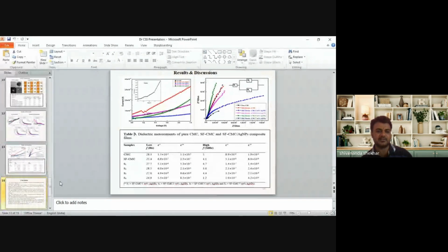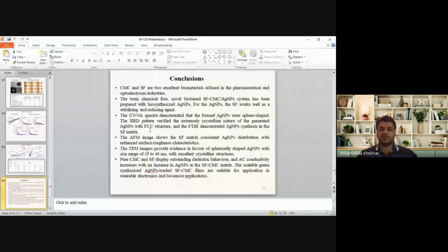And then the conclusions. CMC and silk fibroin are two excellent biomaterials utilized in pharmaceutical and optoelectronic applications. The toxic-chemical-free novel biosynthesis method we have adopted for the synthesis of silver nanoparticles. We have done UV-visible, XRD, FTIR, and also AFM and TEM. TEM confirms the formation of nanoparticles of around 35 to 40 nanometers with highly crystalline behavior. And the increase in the concentration of AgNPs in the SF-CMC matrix gives very good properties, suitable for wearable electronic and biosensor applications.